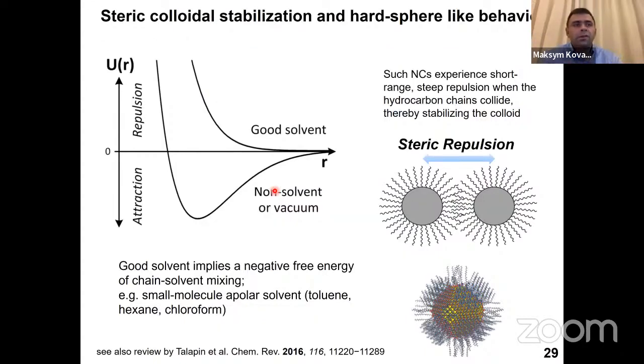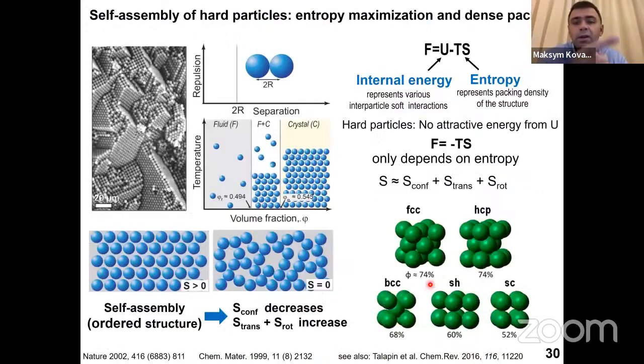How it works: it works that easily only for colloids which are so-called sterically stabilized, with apolar capping ligands like we have for perovskites, so that the particles experience very short-range repulsion, but are otherwise non-interacting at longer distances. So this is a steep interparticle potential in a good solvent. This also occurs when you choose the solvent correctly. It has to be an apolar small molecule solvent. When you have that case, nanocrystals will spontaneously undergo self-assembly.